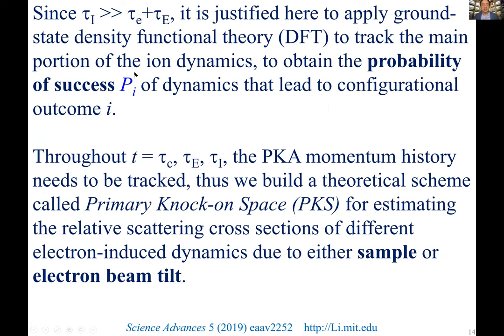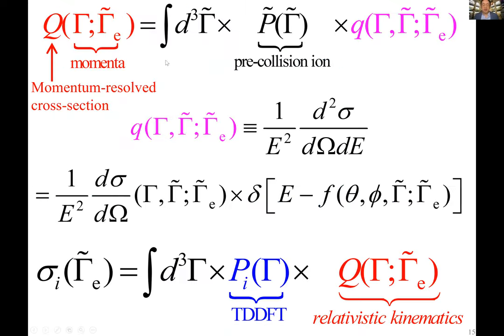And so we can actually just use the DFT simulations to track the trajectory, track the momentum evolution of that primary knock-on atom, and then look at the branching probabilities into these different outcomes, where this i runs from 1 to 4, those 4 outcomes that I've shown before. And then this gamma stands for the vector momentum. And then the tilde stands for the momentum before the collision. So without tilde is after the collision.